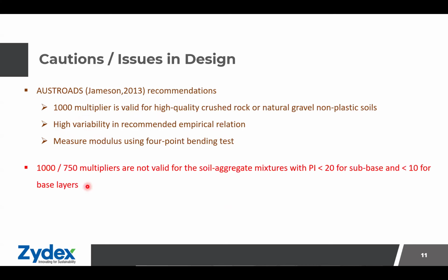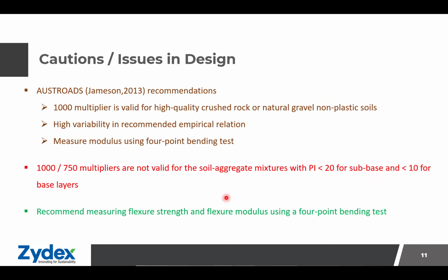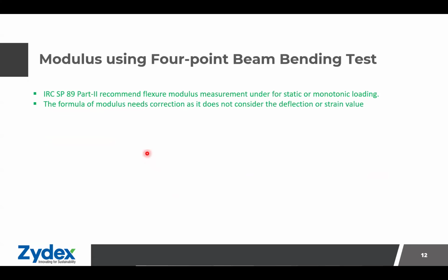So the multipliers that we are using currently are not valid for soil aggregate mixtures with a PI of less than 20 for subbase and less than 10 for the base layers. Therefore, it is recommended to measure the flexure strength and flexure modulus using a 4-point bending test. Now, there is an appendix in IRC SP 89, which talks about the measurement of modulus using 4-point bending test. But the guideline recommends the measurement under static or monotonic loading conditions.